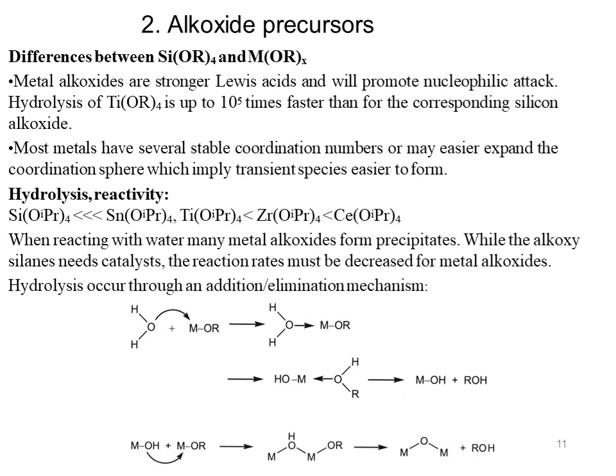Hydrolysis reactivity for Si, Sn, Ti, zirconium and cerium are given below. When reacting with water, many metal alkoxides form precipitates, while alkoxysilanes need a catalyst. Reaction rate must be decreased for metal alkoxides. Hydrolysis occurs through an addition or elimination mechanism. Below in the mechanism we look at what happens if water reacts with metal alkoxide, then the following products are formed, which finally form a metal-oxygen-metal bonded bridge.